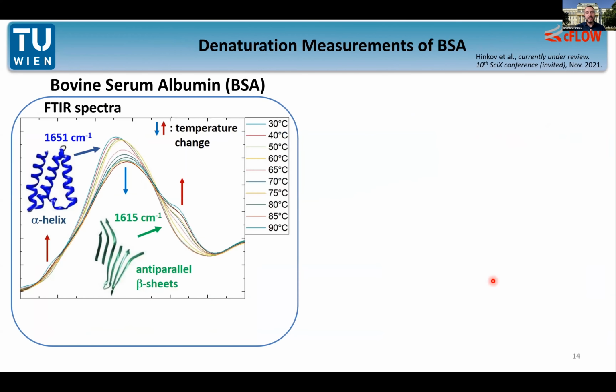Okay, and then, let's look into the experiment. The experiment that we investigated was a denaturation process of a protein called bovine serum albumin. You can see it here. This is its FTIR spectrum. It has a peak here around 1651 inverse centimeters, which is connected to the protein being in an alpha helical structure. If we heat up the protein from 30 to 90 degrees, the denaturation takes place. So the secondary structure is changing, which means that the protein unfolds from this helical structure into antiparallel beta sheets.